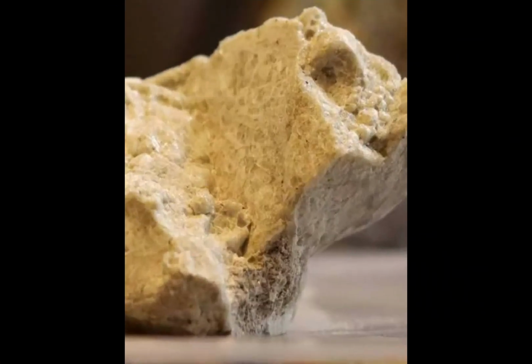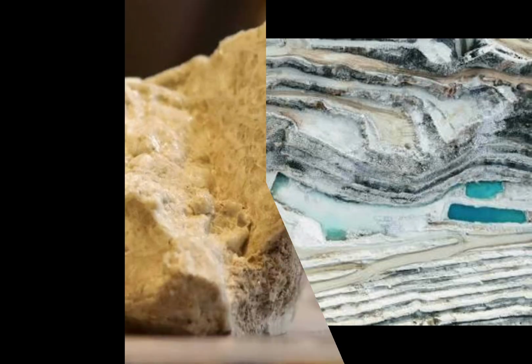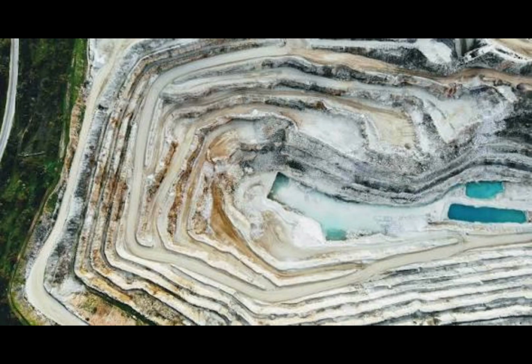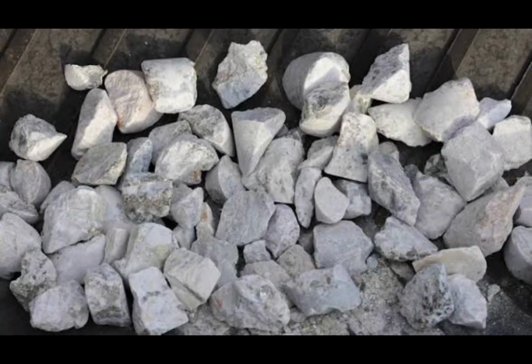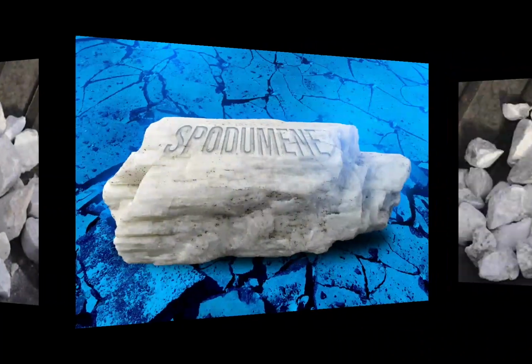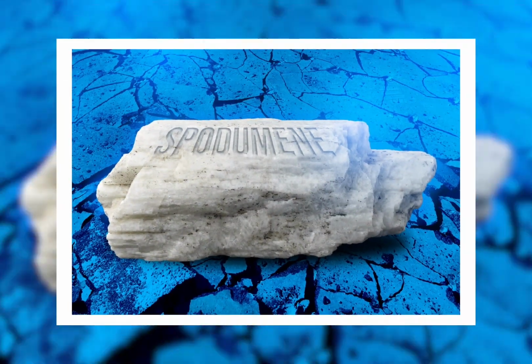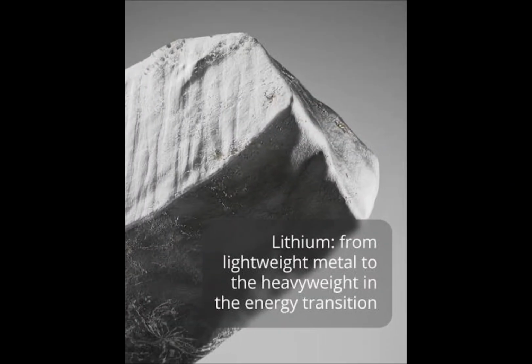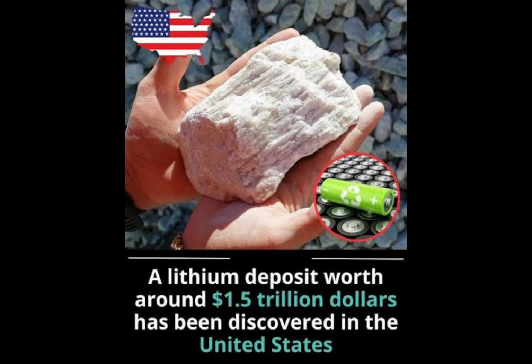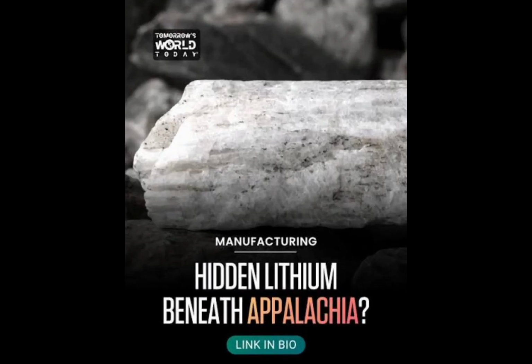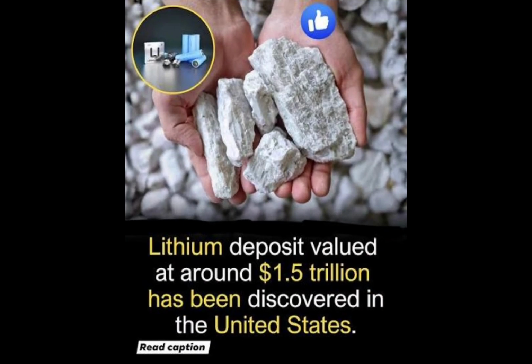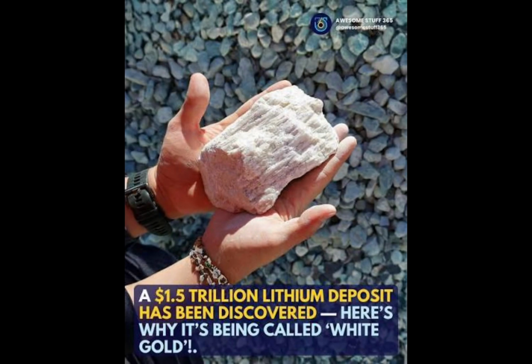More recently, as Chiang was brainstorming ways to chemically break apart the most abundant lithium-bearing mineral, spodumene, he thought back to that etching cream. Spodumene, like glass, consists mostly of silica. Conventional chemistry-based methods for extracting metals from ores preferentially dissolve more reactive elements and leave behind a silica-enriched residue because of the strength of silicon-oxygen bonds.